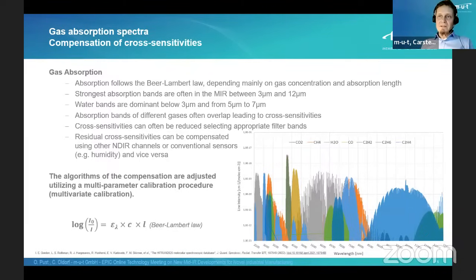This depends a bit on the sensitivity you want to measure. It's usually processed over time. So you have an average over several seconds or up to minutes, depending on what kind of detection limit you want to reach. So this is basically a statistical function of the measurement speed. We could go to below seconds. It's a relatively slow detection method. So usually the limit is around 1 second, or we can go up to 2 minutes to improve signal-to-noise ratios and the limit of detection.